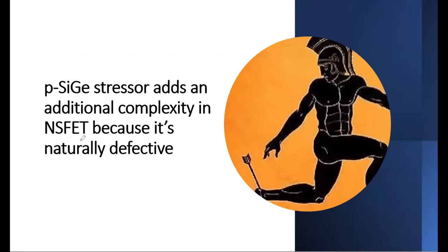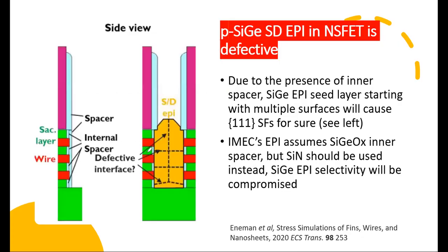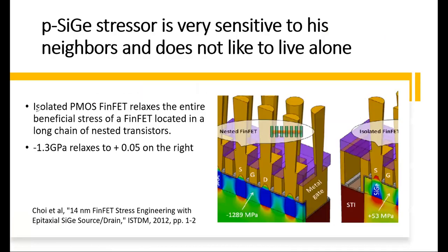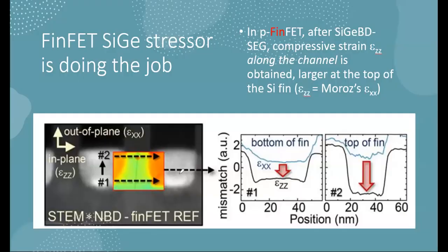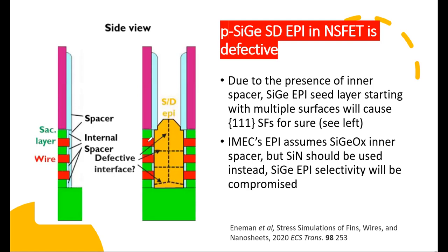And then when you come to nanosheet FET, it's making it much worse. The reason is this. If you look at nanosheet FET, the source strain epi grows from multiple surfaces. In the FinFET world, you grow everything from the same silicon surface. So you could have a nice epi. But on the nanosheet FET, here is your channel. That's silicon. And here is your inner spacer. So you see oxide or nitride.